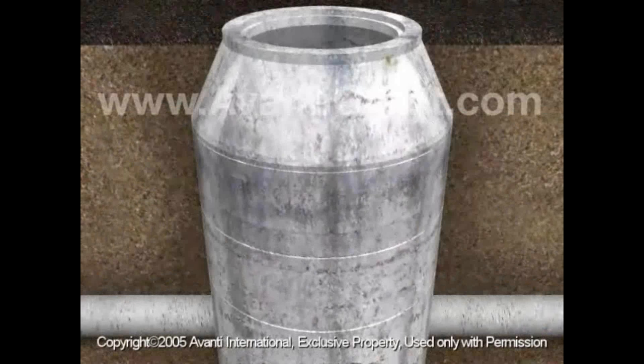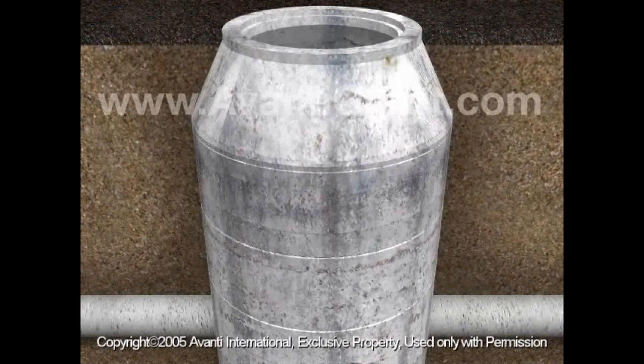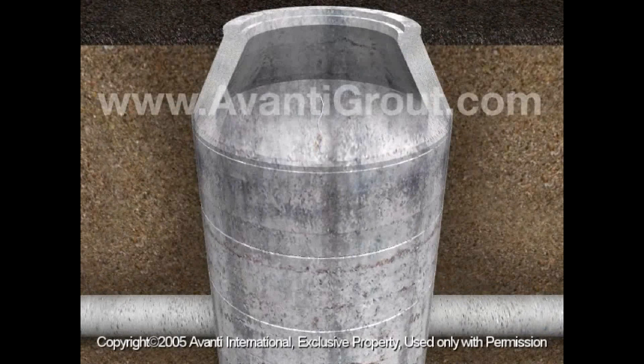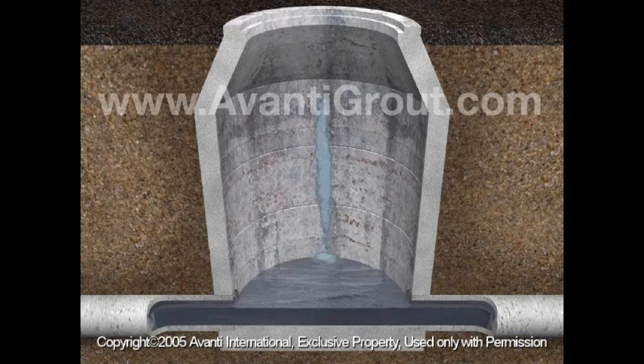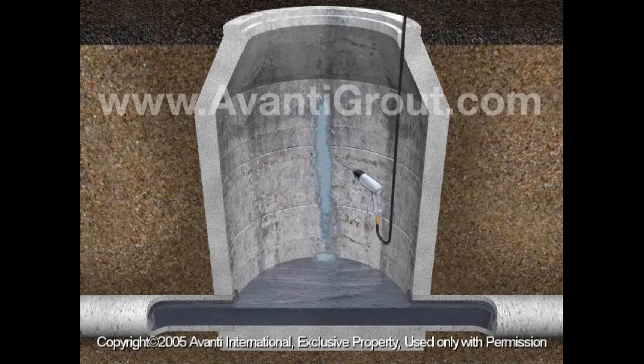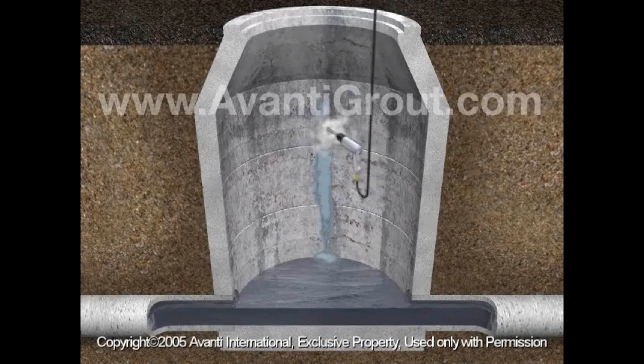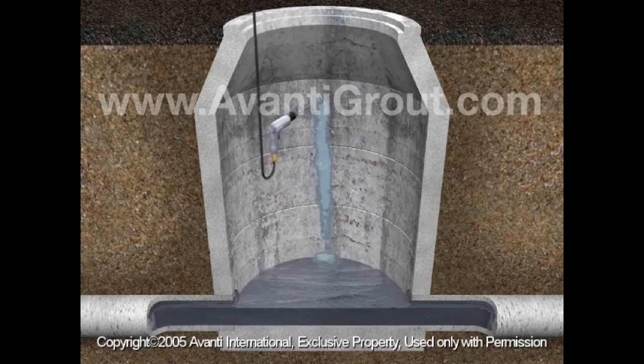In this vertical crack injection animation, you see the leaking manhole, you see the water coming in, you see that injection holes are being drilled from typically the lowest point. You drill at a 45-degree angle toward the crack, a distance off the crack equal to about half the wall thickness. You would typically drill on either side of the crack. You would then flush the cracks with water to remove any debris and then install the injector.